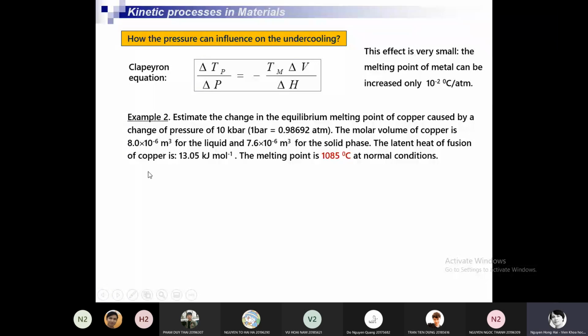The molar volume of copper is 8 multiplied by 10 power minus 6 cubic meter for liquid and 7.6 for solid phase. The latent heat of fusion of copper is 13.05 kilojoule per mole. The equilibrium melting point of copper is 1085 degrees Celsius at normal room pressure and temperature. So you can apply this equation to find the change in the melting temperature delta T.